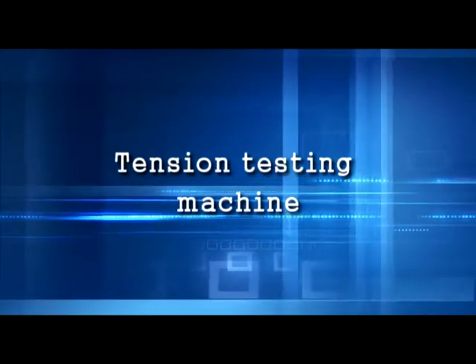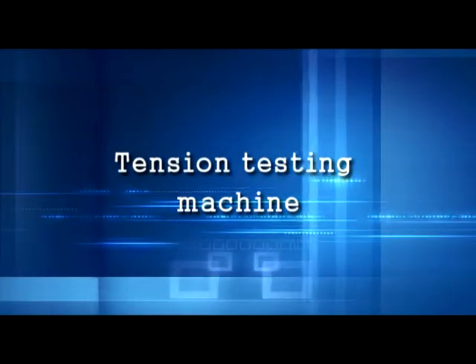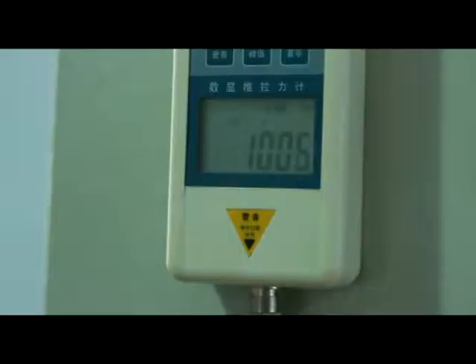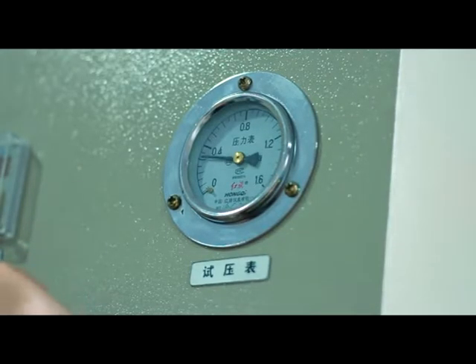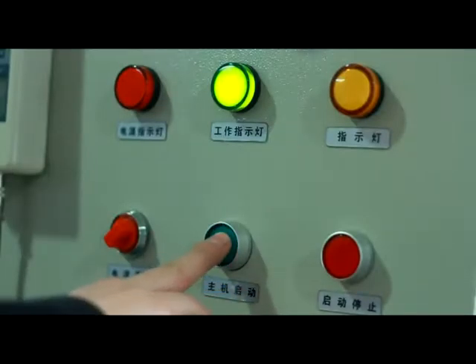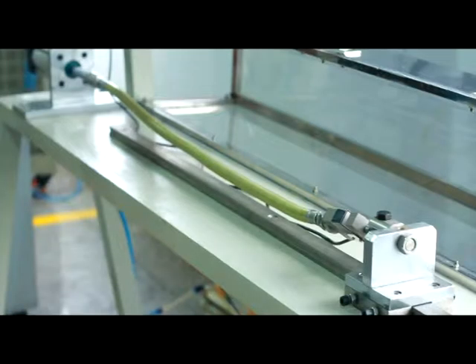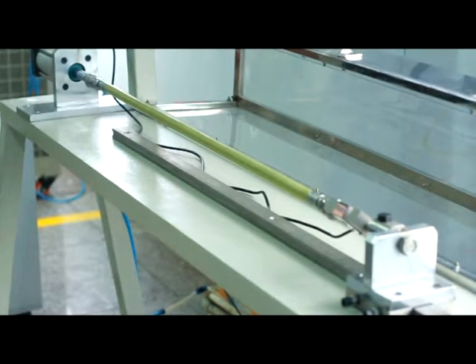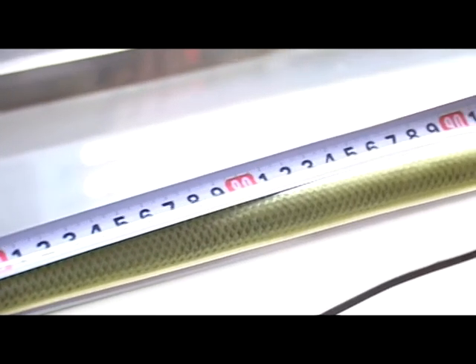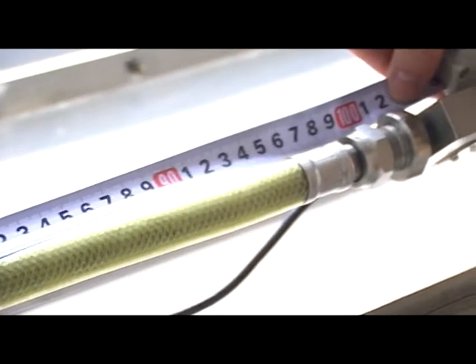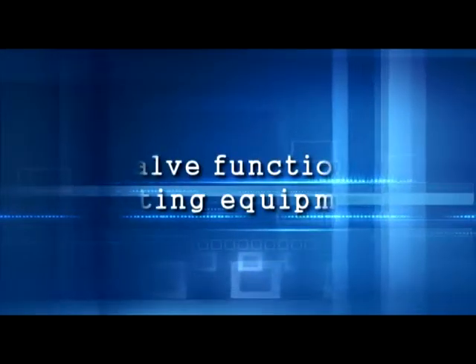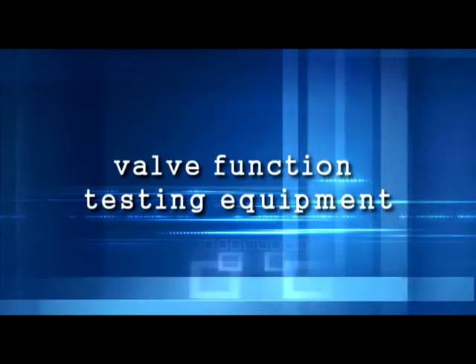Tension testing machine test requirements. Test with 1000 N tension for 5 minutes. No leak happens. After the tension test, the added length cannot be more than 10%. The fixed length of the pipe cannot be more than 3%. Otherwise, it has failed. Valve function testing requirement.